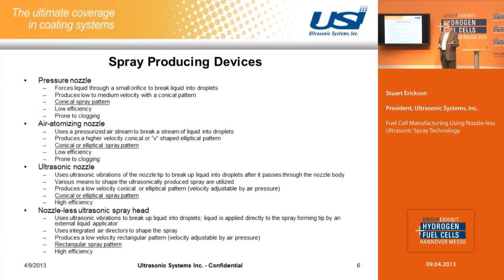Another technology is air atomizing nozzles, which is more like a paint gun. In this technology, you're basically using pressurized air to generate the spray, and you're also using the pressurized air to shape the spray. This technology can apply a conical or an elliptical type pattern. It still is low efficiency because you have air pressure that is making the spray and also shaping the spray, so those two parameters are linked together, so you tend to get a lot of bounce back. That technology is only maybe about 50 or 60% of actually what you spray ends up on the substrate.